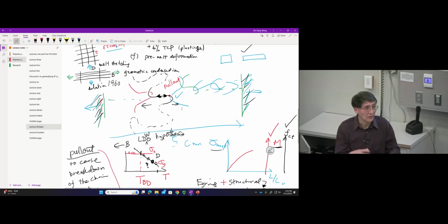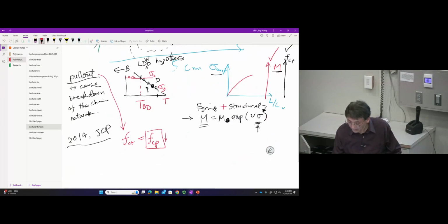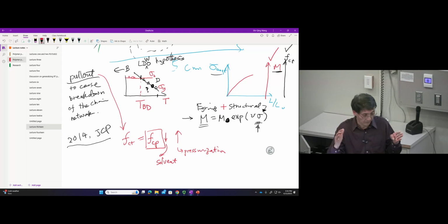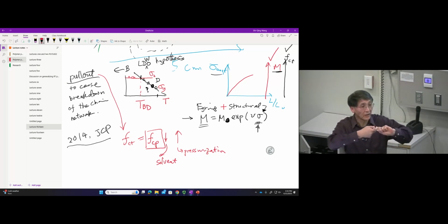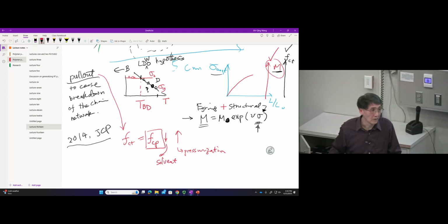What pressurization does, of course, it's not a prediction, but it's an explanation. What pressurization does is, instead of lower the threshold for pull out, it increases the threshold for pull out. So this is the pressurization effect, and this is the solvent effect. So in presence of pressure, it will take more chain tension build up for pull out to occur. By that time, activation already occurred. So you yield instead.